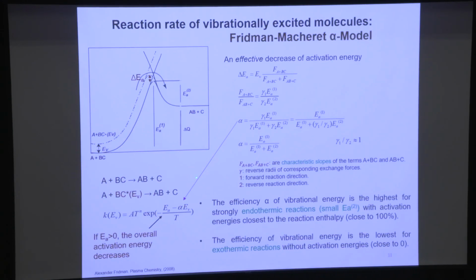For example, one of the big flaws in plasma kinetics involving vibration: you have vibrational molecules involved here, and you calculate the reaction rate. Basically, they're using a correction. For example, the original activation energy is delta E, and then with vibrational molecules, you put a vibrational energy here, you plus an alpha. And that alpha is basically calculating the ratio about the forward activation energy EA here, and the backward reaction about EA2 here. So this is a very rough idea, but unfortunately in plasma chemistry, physics areas, a lot of people are using it.